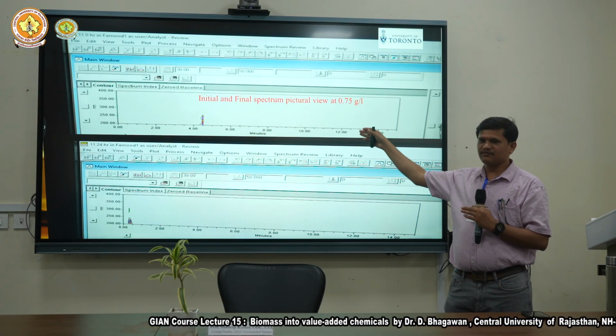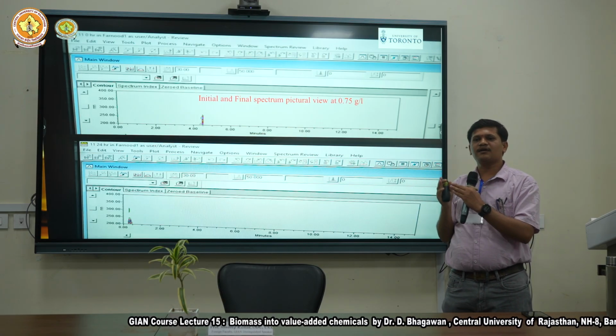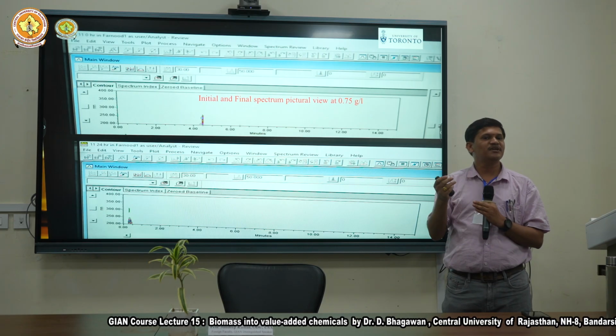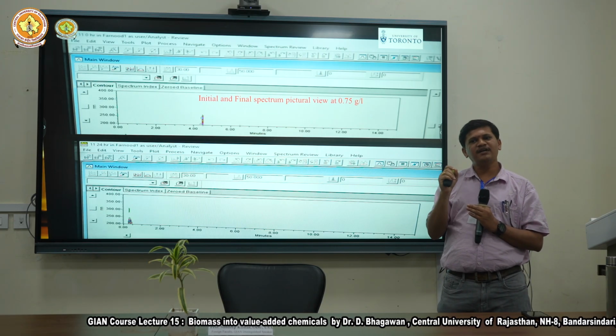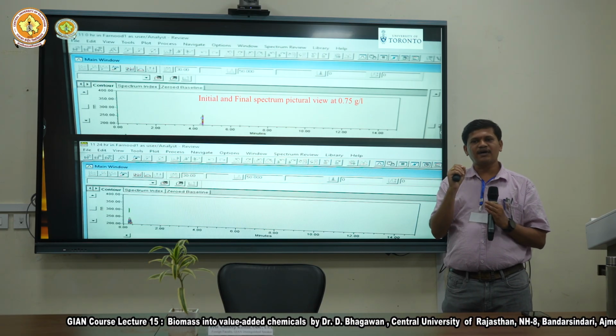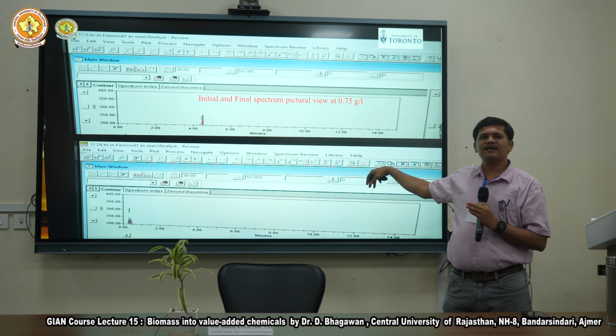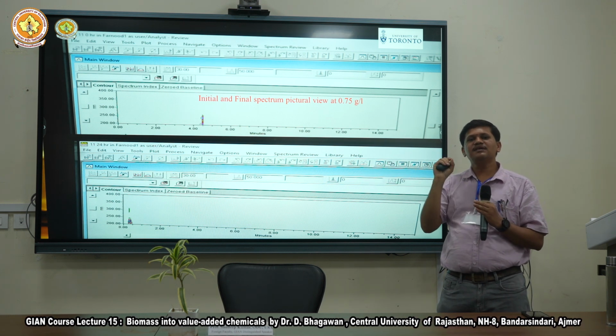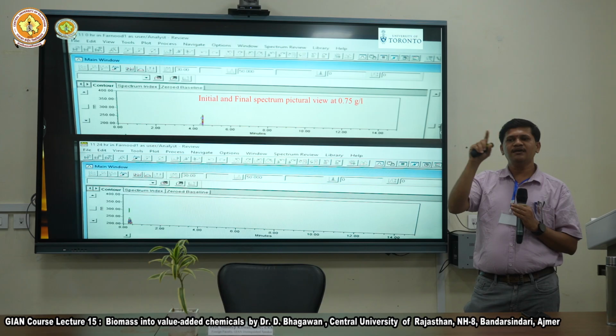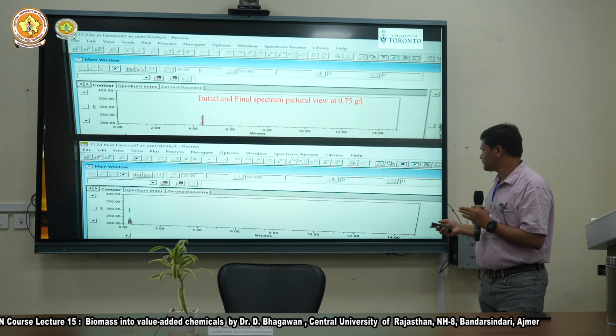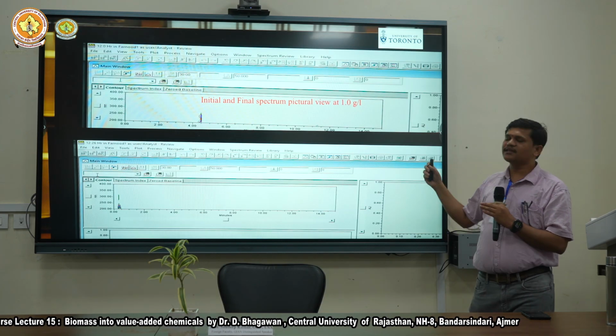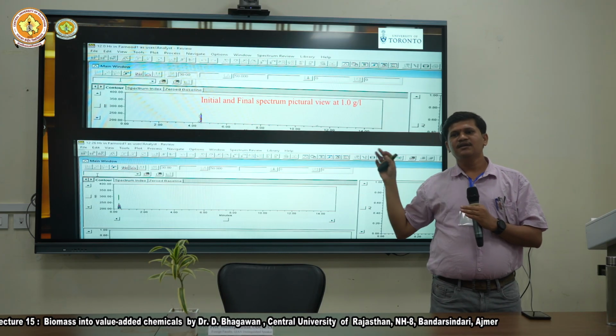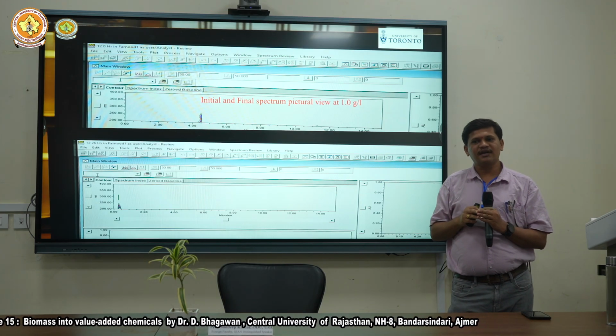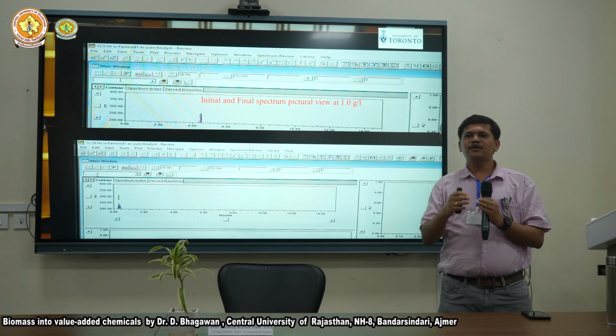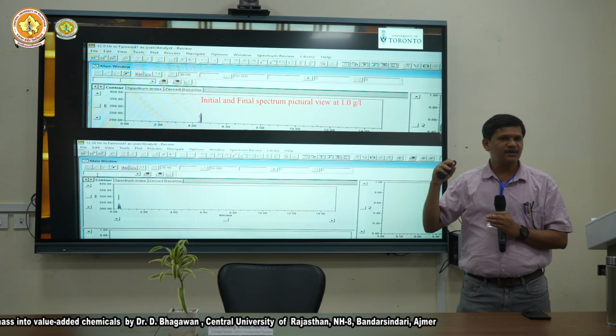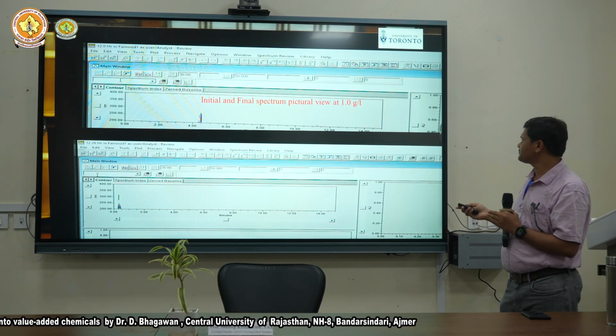With this pictorial view, we can say the compound conversion or formation is very selective and suitable. If you go for this reaction, then we can generate only the selective target compound from the polymeric chain of lignin. This is the lab scale study which we carried out. But if we continue the same thing with the semi-pilot, then it can be continued up to the pilot scale levels.